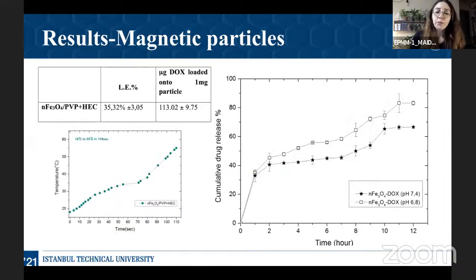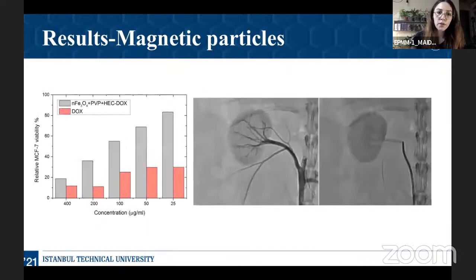When we look at the drug release response at pH 6.8, which is tumor pH, 80% of the drug was released within 12 hours, which was not as rapid as polymeric beads. It was slightly extended. And when we heated our particles under alternating magnetic fields, we saw that they reached 55 degrees Celsius within 110 seconds, which indicated that our particles could be used in magnetic hyperthermia treatments.